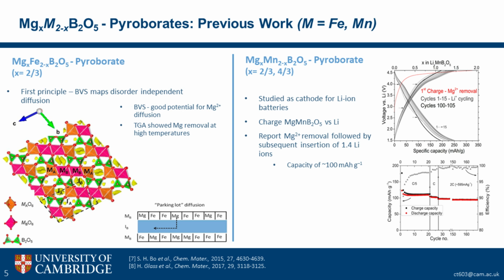And in this case, they studied the cathode material for use as a conversion cathode in lithium-ion batteries. They reported a removal of all the magnesium and insertion of 1.4 moles per formula unit of lithium ions and a reversible capacity of 100 milliampere hours per gram. They didn't show a lot of post-cycling analysis to prove this, and that will end up being an important takeaway message from my talk, hopefully.